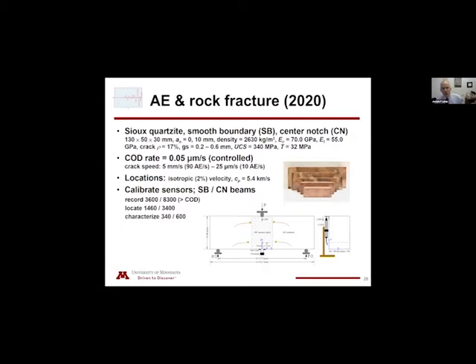The results I'll be showing, although we tested various size beams, so we did perform a size effect analysis to look at conditions associated with linear fracture mechanics size beams. I'll be showing results for a sub-size specimen. So the span is 130 millimeters, the height is 50, the thickness is 30. Of course, a smooth boundary has no initial notch. The other beam that is with the center notch is nominally 10 millimeters in length.